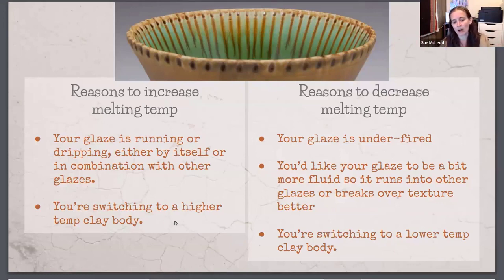Or if you're switching to a higher temperature clay body, you can increase melting temperature so that your glaze will melt at a higher temperature and it won't run all over the kiln shelves. Reasons why you might want to decrease your melting temperature: if you determine your glaze is underfired. So maybe you have a matte glaze in the glossy region of Stull and there's no other reason why it should be matte. So you might want to lower the melting temperature because if it's on functional pieces, you want your glaze to be completely melted, or find a new glaze. If you like the matte glaze, then just find a new matte recipe for that temperature.